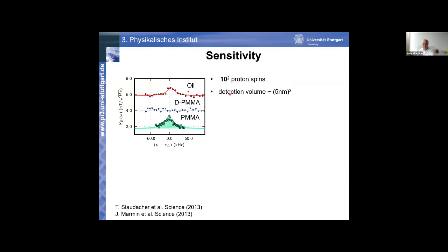And here you see such an experiment. On the y-axis, I plot essentially the time-varying magnetic field. This is why it does not say magnetic field, but S of B as a function of omega. But you can forget about that, right? Once again, the unit is nanotesla square root of hertz. And now I plot it as a function of frequency, which essentially is 1 over the pulse spacing of the pi pulses I apply to my sensor. And it is centered at the Larmor frequency I expect for proton spins.